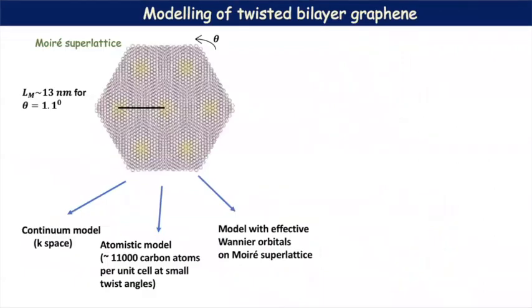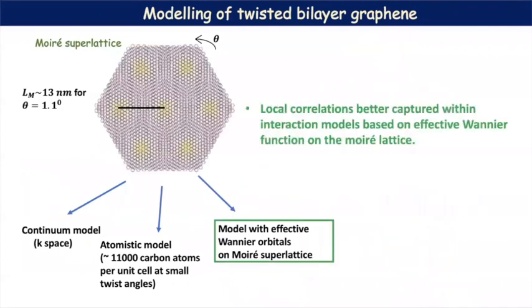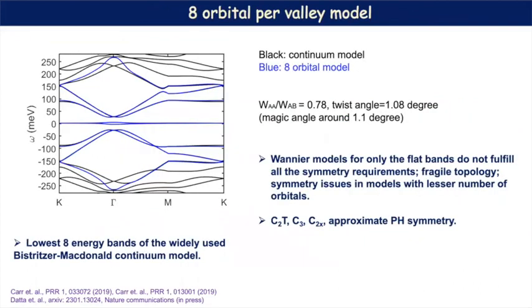There are different approaches that can be taken to model it. But the approach that we take is to have a model with effective Wannier orbitals on this Moiré superlattice. And the reason for that is, one, the physics is happening on the Moiré length scale, and the local correlations are better understood if we have an interaction model on a lattice. So what we have is an 8 orbital per valley model. And this model gives us the 8 low energy bands of the widely used continuum model called the Bistritzer-MacDonald model.